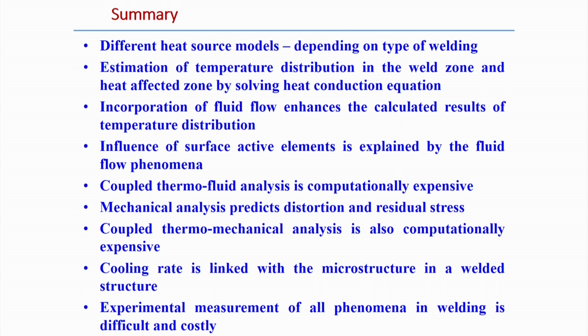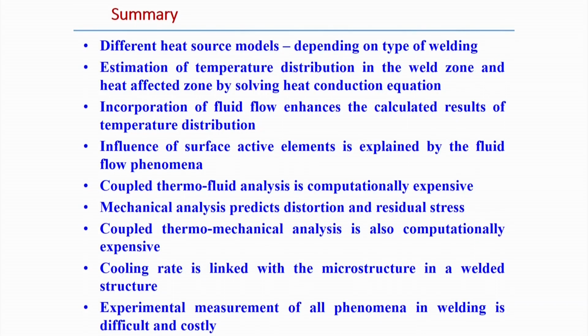Then mechanical analysis predicts the distortion and the residual stress, but it needs the temperature distribution as an input to predict the distortion and residual stress in the welding process. Of course, coupled thermomechanical analysis is also computationally very expensive. And then the cooling rate: if we know the temperature distribution from this numerical model, we can estimate the cooling rate, and that cooling rate can be linked with the microstructure in a welded structure. So, simply by calculating the cooling rate, it is possible to predict the microstructure present in the welded joint.